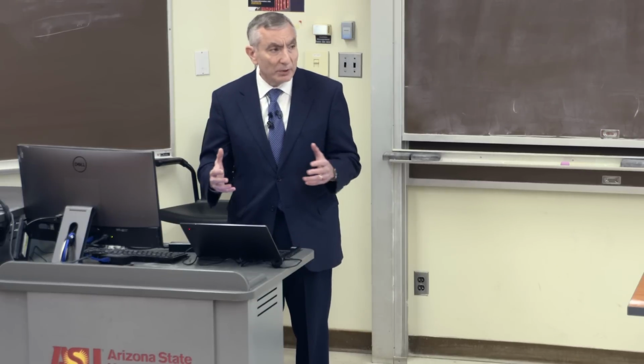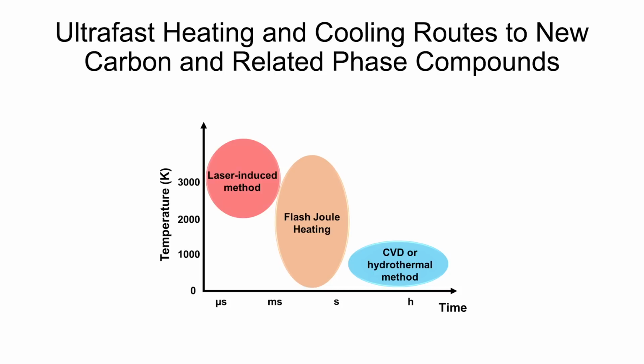This transitions right into what we're going to talk about today, and this is this ultra-fast heating and cooling route to new carbon materials. And so that laser-induced graphene method is using systems that are exciting in about the microsecond time range, and the systems heat between 2500 and 3500 Kelvin. But what we're going to focus on today is not this, and not the CVD routes to grow graphene, but flash joule heating.